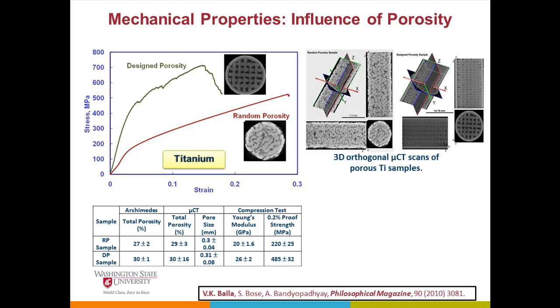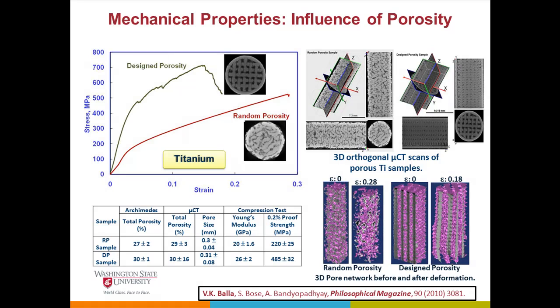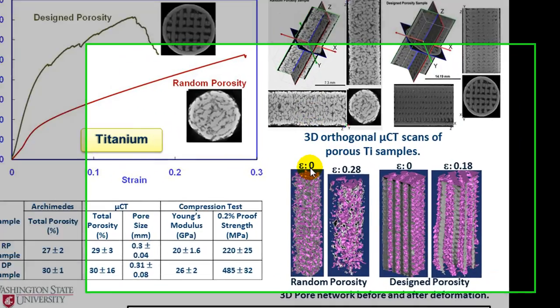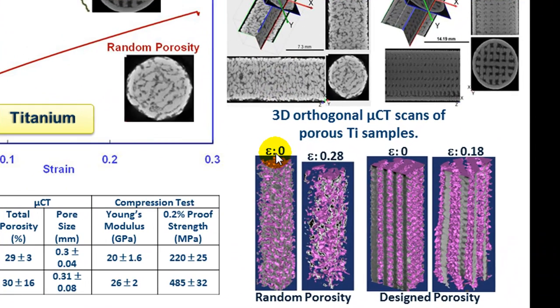So what we did is build random porosity structures and design porosity structures, and then under different loads and times, we performed micro CT scans to understand how the pores deform as a function of time. This is a design porosity before loading, and this is after some time.